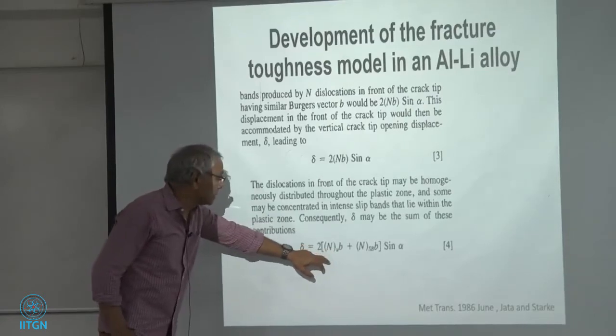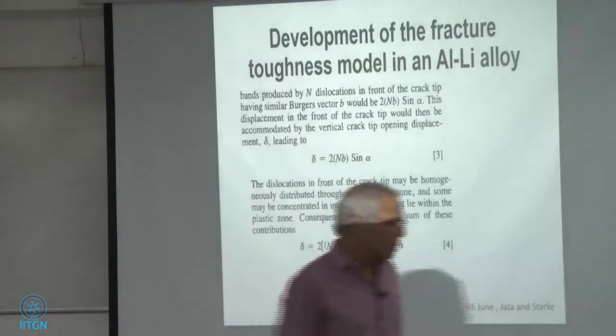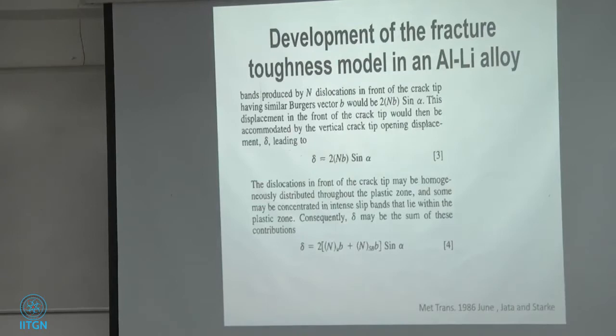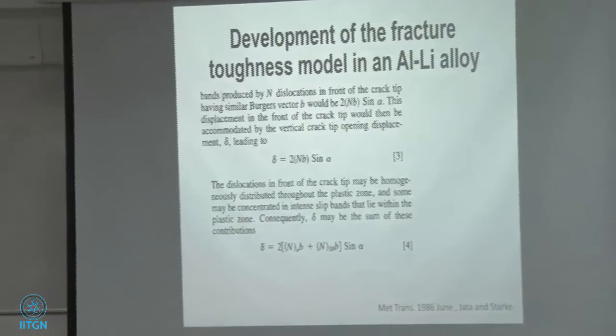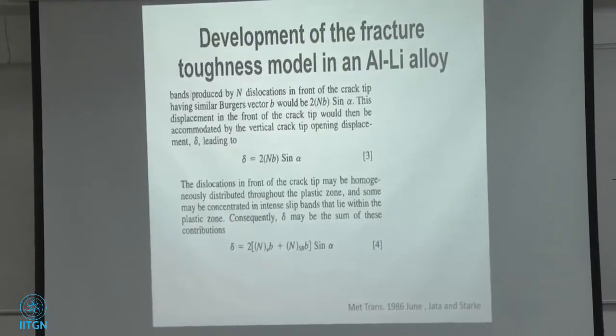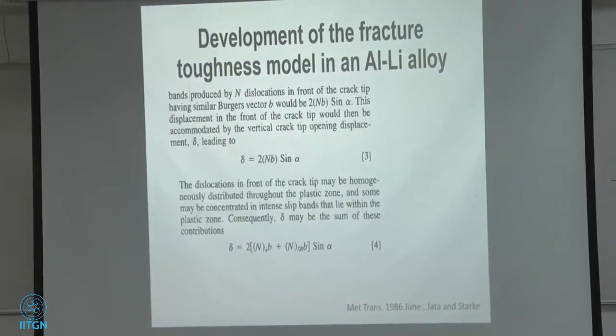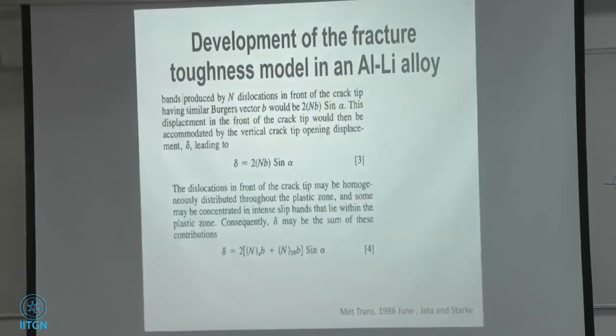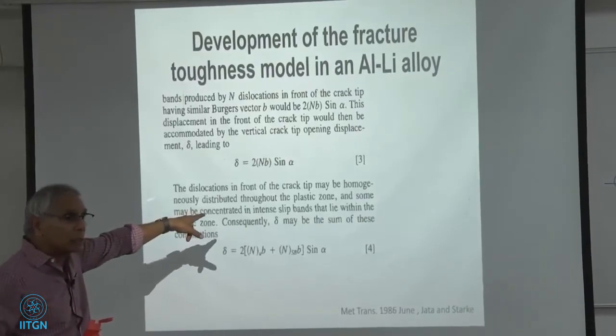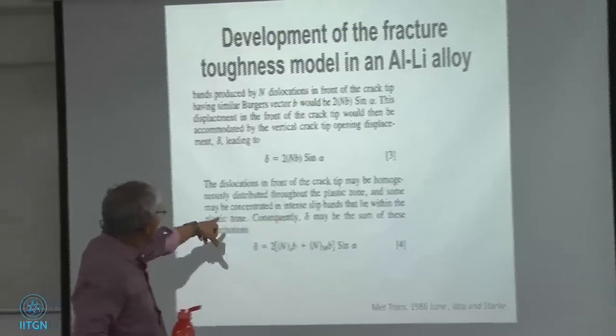Some of them are homogeneous, some are heterogeneous. Because not all dislocations are in the bands. There are other dislocations too. You have to consider both of them. You see what I wrote there, the paragraph, right? The dislocations in the front of the crack tip may be homogeneously distributed or heterogeneously distributed in intense slip bands, right?